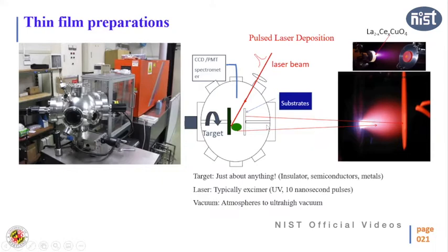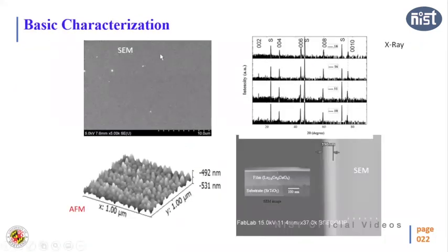Once we prepare these thin films, we do some basic characterization. The first thing to check is whether the film is quite uniform or has some patches. To make sure, we look at the surface of the film, which is very clean and clear. We also do X-ray to check the crystallinity of the sample, and whether it's growing epitaxially or not. Sometimes we do AFM to measure the roughness of the film. We also have to know the thickness of the film, so we do SEM, scanning electron microscopy. This is the film sitting on the strontium titanate substrate. The thickness of these films is in the range of 100 to 200 nanometers, depending on our measurement requirements.